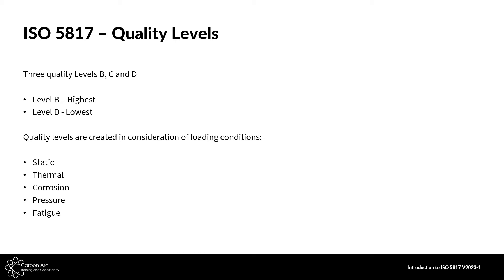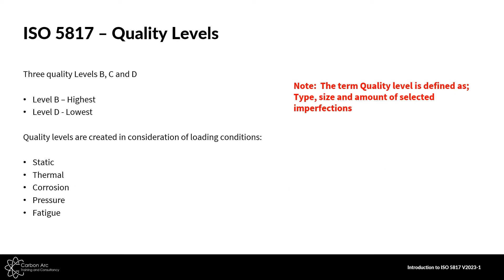It also captures a lot of different loading conditions — static, thermal, corrosion, pressure, and fatigue. Some things to note, especially in fatigue, is that we've got to fall back to Annex C within 5817, because it makes some changes to the main document to tighten up defects which are going to affect fatigue life.